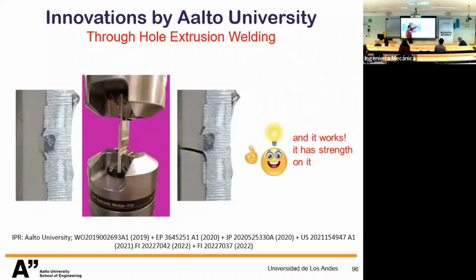Okay. So we use these extrusion matrices. They are made of titanium that has very low thermal conductivity, so they protect the energy, the thermal energy that we transfer from the aluminum into the polymer. And they are harder than the aluminum, so they are used as extrusion. So we extrude aluminum into the polymer, protecting the polymer from the energy necessary to extrude. And then we take this in to produce now joints over joints.